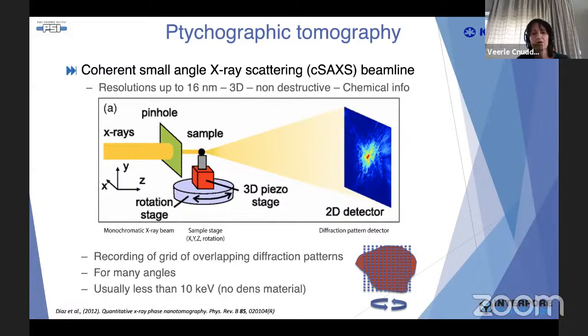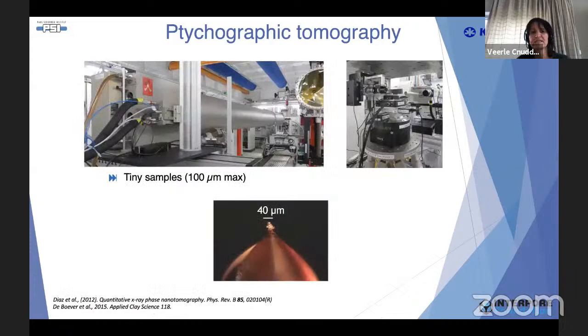What you do is you need a very small sample, which you position on your sample holder. Your source of X-rays is produced by the synchrotron, and then you have a detector that records a grid of overlapping diffraction patterns over many angles, registering your sample in a non-destructive way. Here you see the setup.